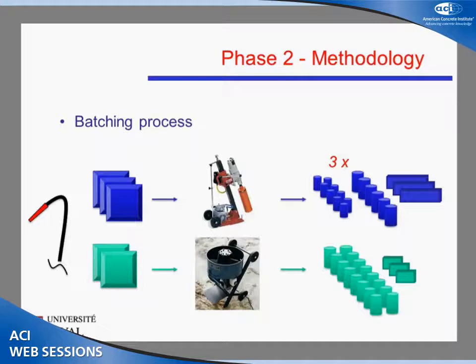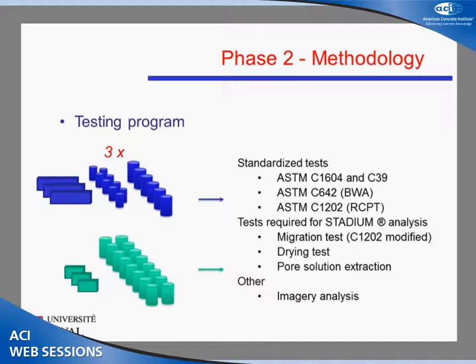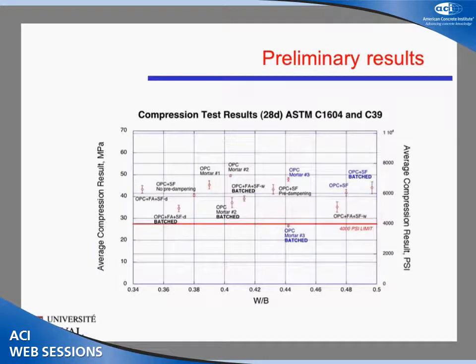And finally, for the batch, we produce normal 4-inch compression cylinders. We also produce panels that go from about this big to that big, from about 2 feet to about 1 foot. We want to do a quick imagery analysis, something that's been in the works at Laval. Instead of doing an L-bar, we just want to have an idea of how the large voids are spaced in the samples. So that's another thing we're considering. Now the testing program is pretty much the same as my colleague in phase 1. We have the standardized tests, the compression strength tests at the top, followed by the C642 and C1202, and of course the tests that are required for Stadium analysis that we input into Stadium Lab. And followed by the imagery analysis, which I won't get into very much, but it's a very promising prospect.